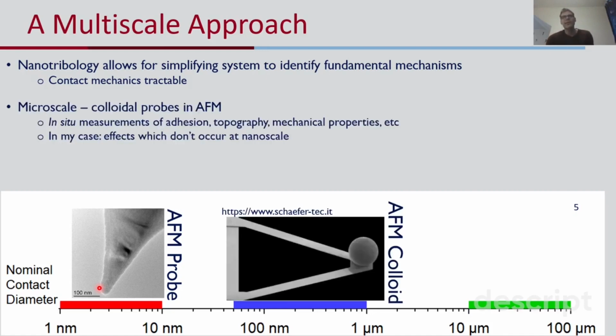The second length scale with contact diameters below a micron is what's referred to as the microscale. And so in this case, the experiments I did, we glued a steel colloidal ball on the end of an AFM cantilever and then did sliding experiments in the AFM again. And this is useful because we can measure the various parameters that we can get from the atomic force microscope, like adhesion and topography. But additionally, in this particular material system, we actually see effects which don't occur at the nanoscale. And so that's going to be important for what we talk about later.